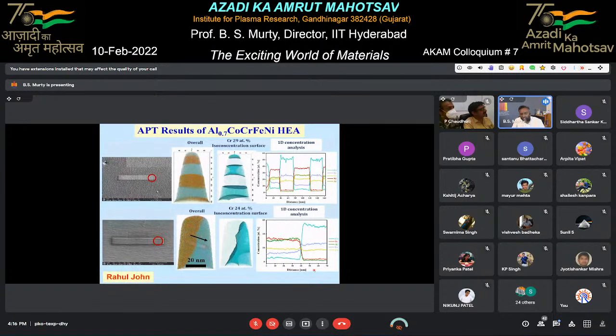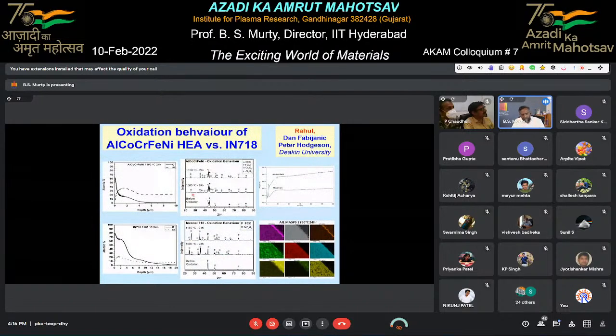We can also see if it is a 2-phase material, how the elements are distributed. Okay, so here is a case where you can draw a line, vertical line from bottom to top, and then see what is called compositional profile. How is the compositional profile in this material? Please note that this whole from top to bottom is all about 100 nanometers. So within 100 nanometers, I am able to see how the elements are distributed. All this is possible.